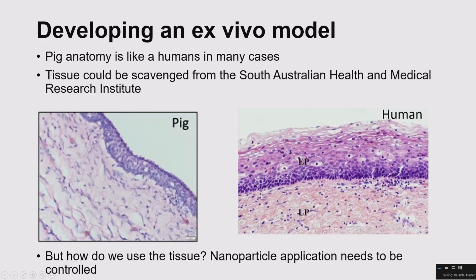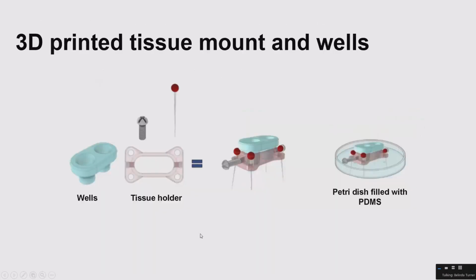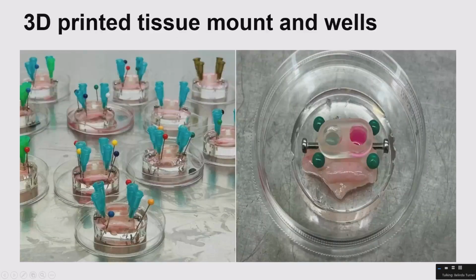So thankfully pig anatomy is like humans in many cases, so we could scavenge pig tissue from SAHMRI. But then how do we use this tissue? Nanoparticle application needs to be controlled. So she's developed these 3D printed wells and this tissue holder where we would pin the tissue across this tissue holder with these pins, attach these wells and adjust the height with these screws, and then put this onto a PDMS filled Petri dish where we could put media in, so that's what that looks like. So that allowed for a really high throughput testing of her nanoparticle formulations.